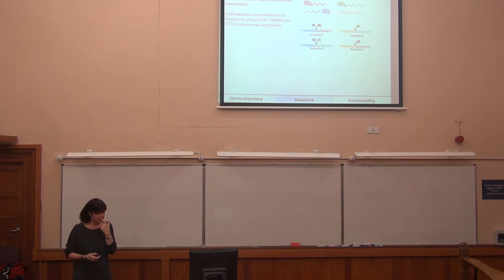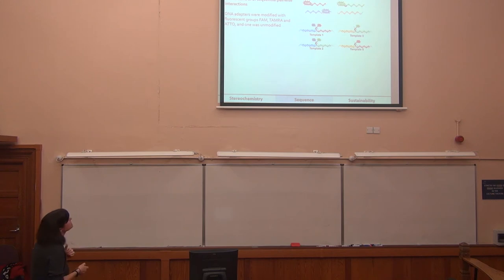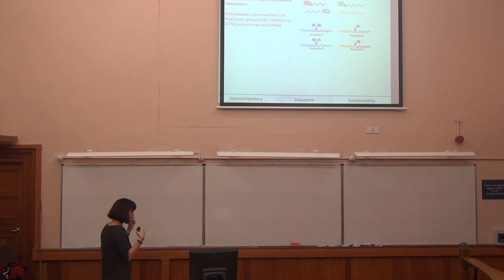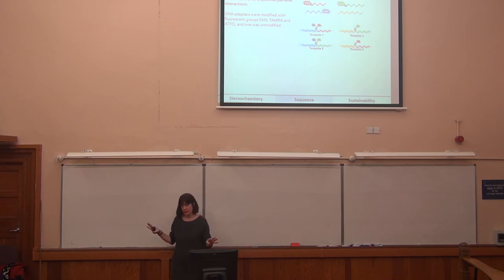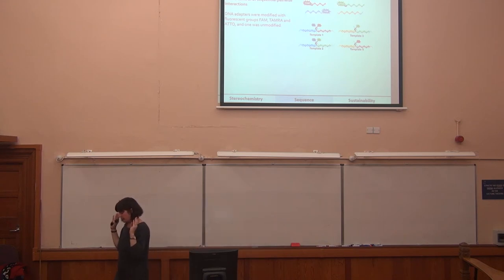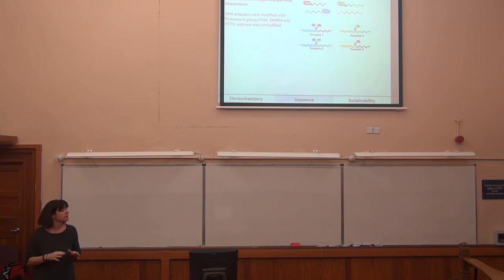And to prove that this might work, one of the proof of concept experiments we did was to take four different DNA strands, three of them coloured with FAM, TAMRA and ATTO, and one just labelled yellow here without a dye, and look at them in one pot. The important thing is we're not purifying at each step; we want to be able to add an instruction and wipe an instruction without purification. So we're doing it all through sequential instruction addition without purification.